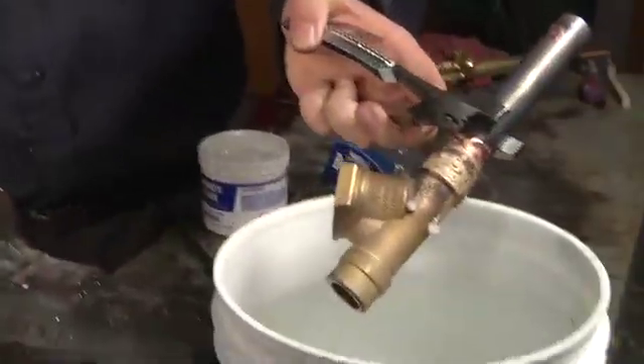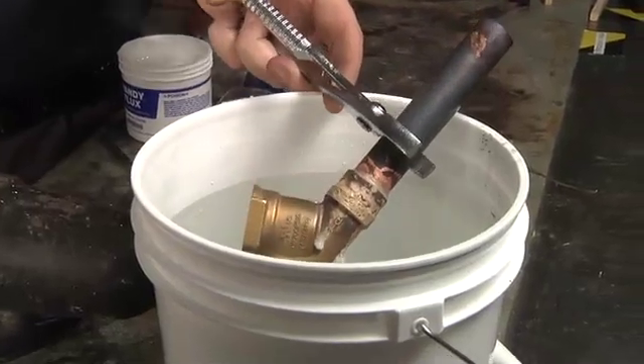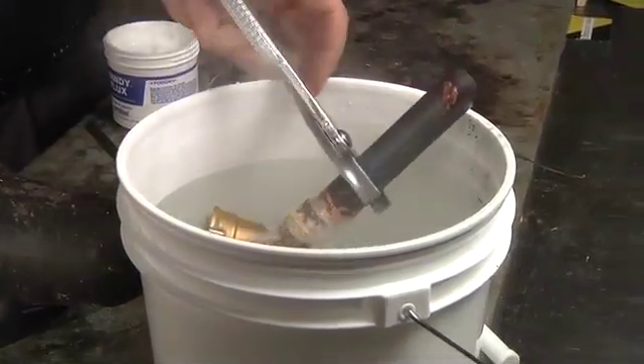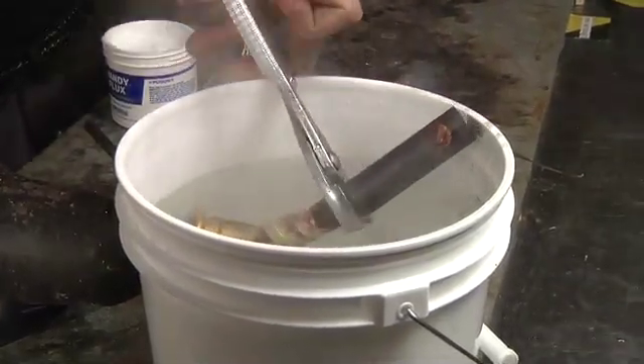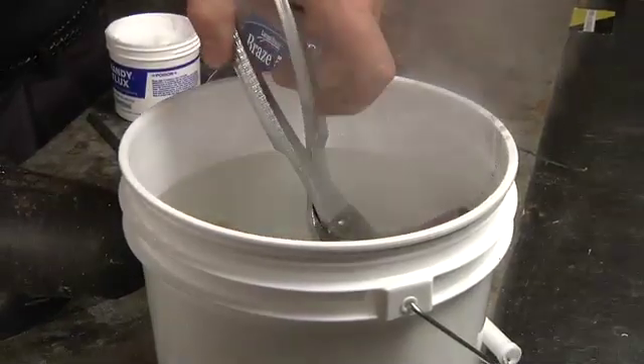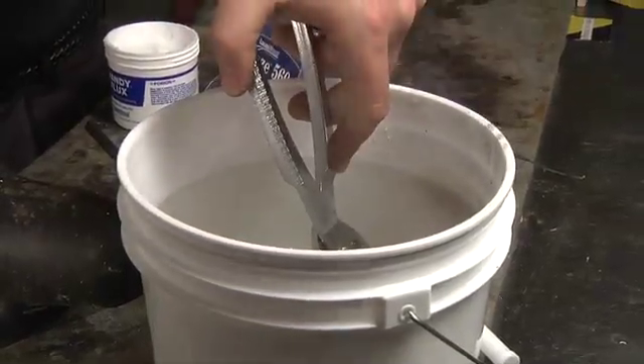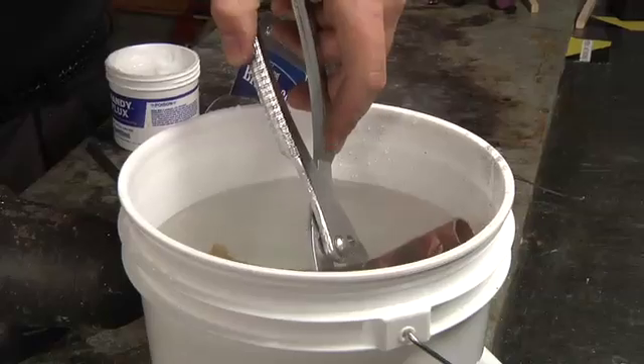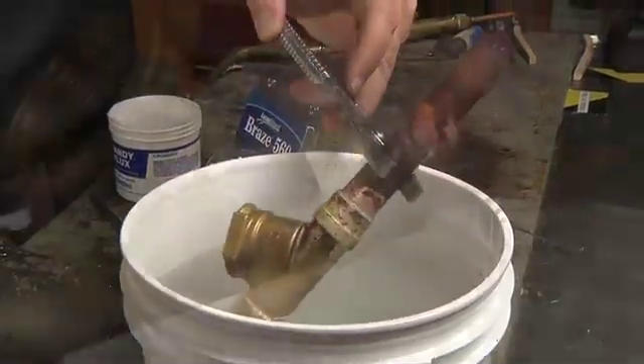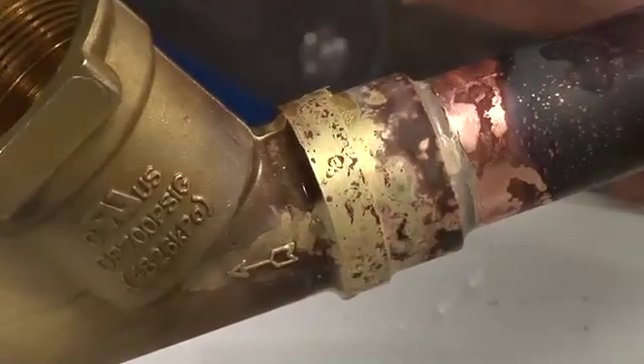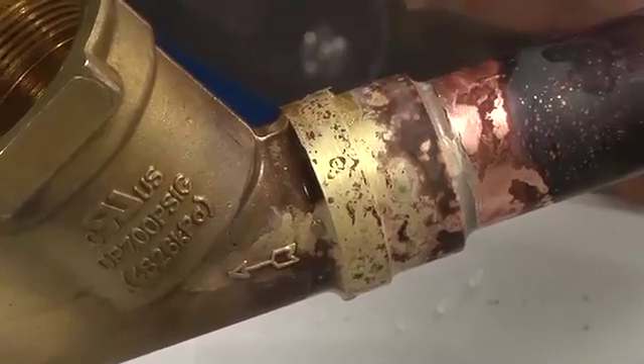Flux residue can also be removed in a bath of hot water, as fluxes are salts and will dissolve well into an aqueous solution at higher temperatures. The flux residue must be removed, as the flux is corrosive. After brazing, inspect the joint for any voids or lack of fill.